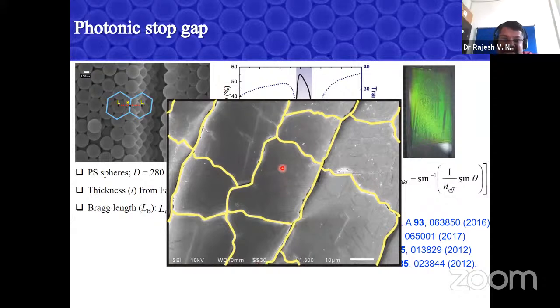Okay, but in reality, this kind of measurement is not possible from this. In the lab, when you measure your very large area sample, these samples are divided into these kinds of bits and pieces. So you can see the scale is 100 micron. So people were convinced around 2010 to 2015 that these self-assembled systems are not good for many optical experiments because they have a huge number of disorders. But we thought maybe a clever experiment can avoid this.